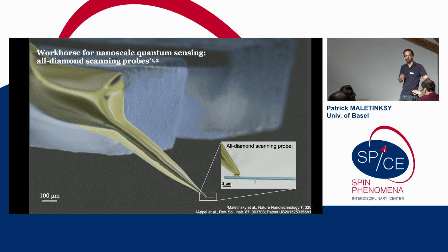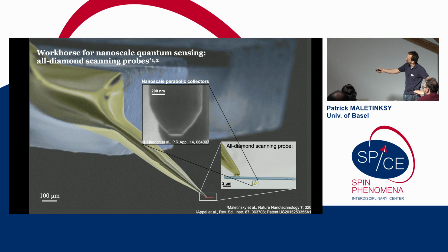the nanoscale sensing. So one of these technologies we developed are these scanning probes that host individual NV centers. So here you see an electron micrograph of an all-diamond scanning probe tip. At the very end, you have a single NV center, which I draw here for you. That thing is attached to a quartz tuning fork. That's a force sensor that allows us to do force sensing and bring this NV in close contact with a sample of interest to do magnetometry. There's a bit of engineering involved here. So if you zoom into these tips, those are in fact photonic nanostructures that we're trying to shape in a way that the emission of the NV center preferentially goes upwards to our detector, which sits somewhere up there.